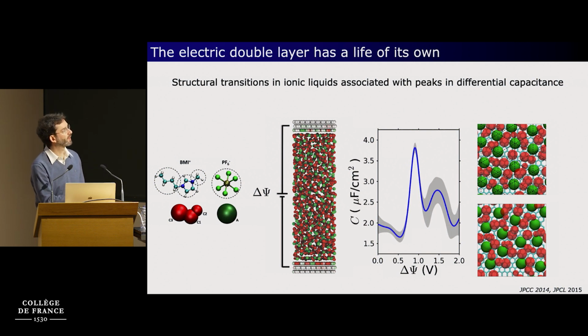So here is the same capacitor as I've already mentioned, with the graphite electrode and the ionic liquids modeled with a coarse grain electrolyte. And here is the differential capacitance as a function of voltage. And you see that there are many features. And for example, we could show that this first peak in the differential capacitance is associated with an order-disorder transition in the first adsorbed ionic liquid layer.